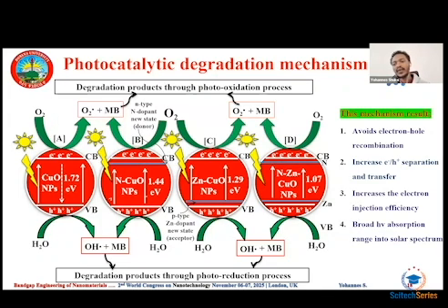In the same fashion, when we modify the surface of copper oxide with nitrogen and zinc, we observe two new states above the valence band and below the conduction band, which narrow the band gap for this material to 1.07 electron volt, which avoids the recombination of holes and electrons, and generally this system leads to alteration of the electro-optical response of the materials.